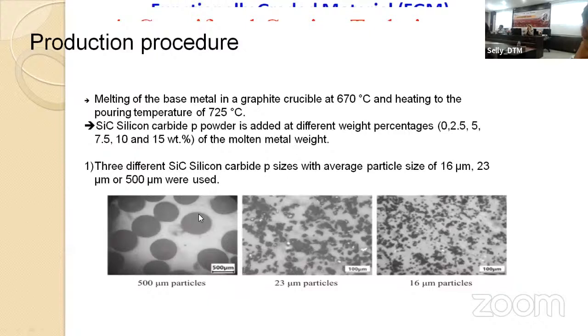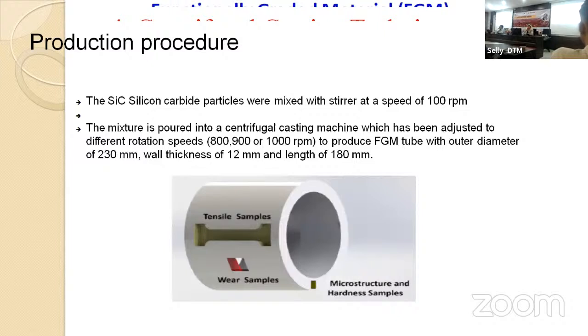And there are three different sizes of silicon carbide added to the metal matrix. For example, a 500 micrometer particle, a 23 micrometer particle, and the smaller one is a 16 micrometer particle, added to the aluminum. I want to show you the procedure.